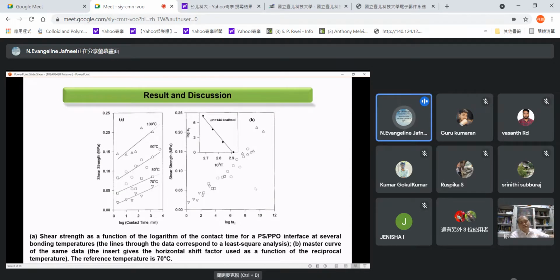Next, the shear strength of the PS-PPO interface is given. We know that the PS-PPO blend was miscible over the full range of composition. Here the shear strength versus log contact time graph was given. It shows an increase in shear strength with the increase in bonding temperature. Here the master curve of 70 degrees Celsius was chosen, and with the help of the master curve, it was plotted. Shear strength versus shift factor is given. The corresponding Arrhenius plot is also shown. With the help of the Arrhenius equation, the enthalpy was calculated as 144 kilocalories per mole.